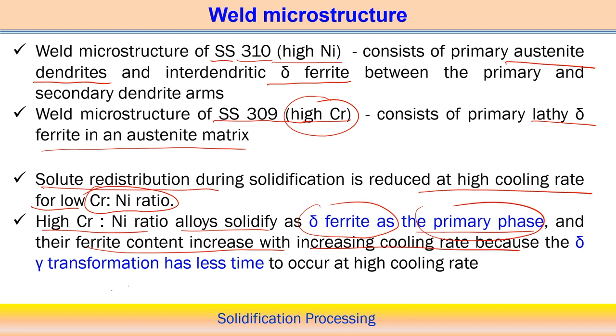So with increasing the cooling rate, the ferrite content actually increases in this case, because the delta to gamma transformation has less time. So the transformation time is less. When the cooling rate is much higher, less time is available to transform from one phase to another phase. So that is why we can increase.